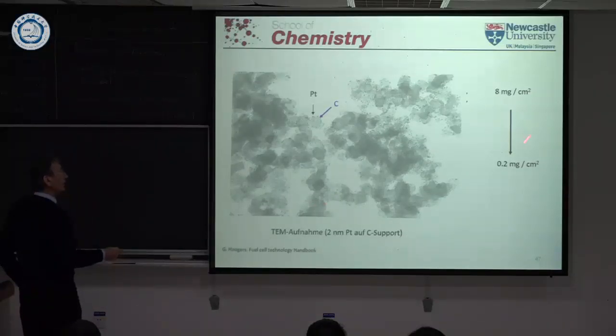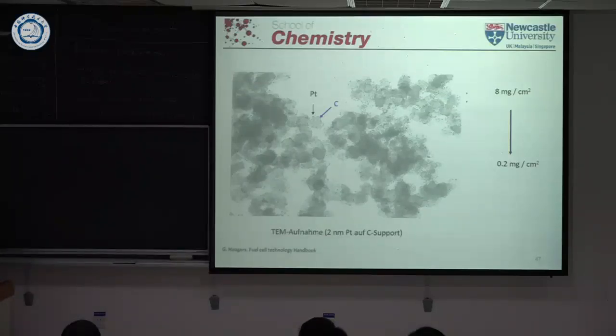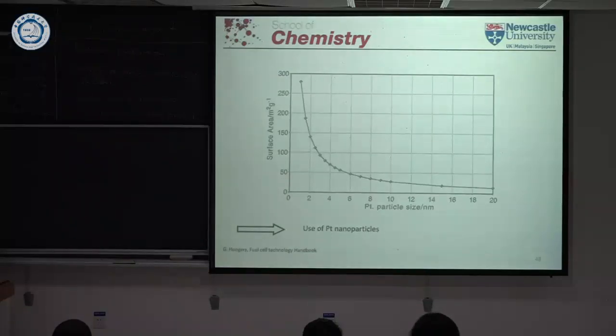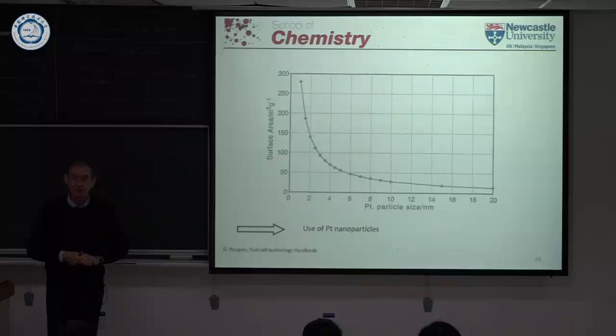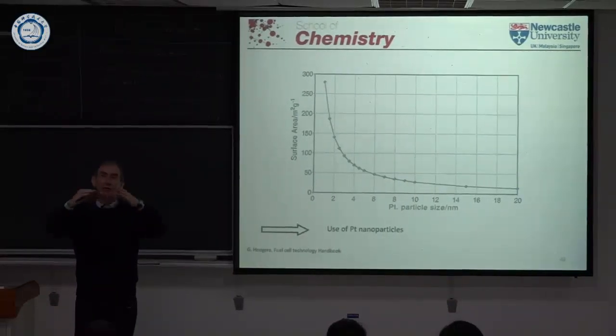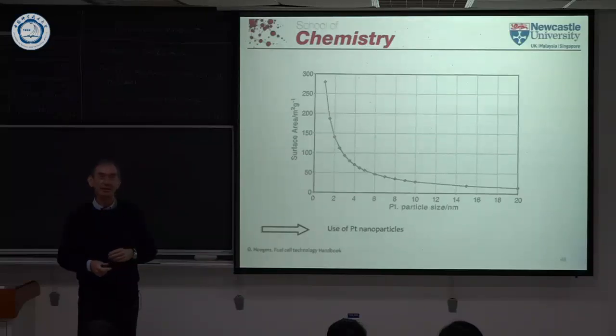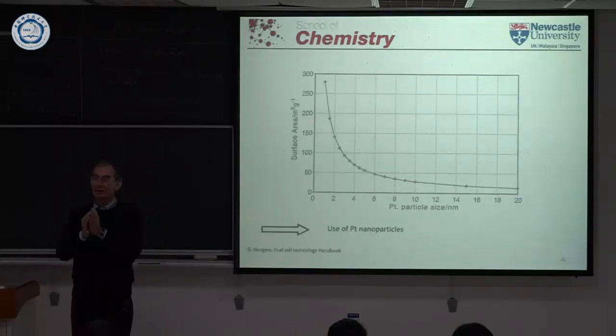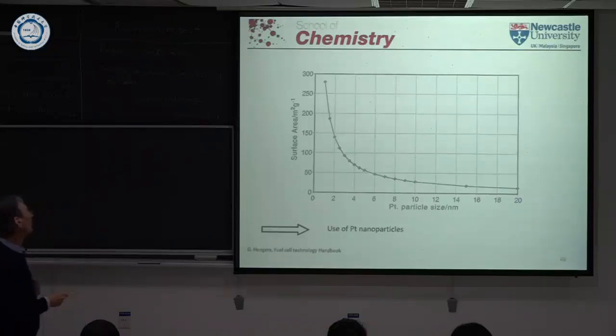And then you can vary actually the coverage, how much metal you put actually per square centimeter. That's shown here. That's sort of the variation, 8 milligram down to 0.2 milligram. Now I told you before, since platinum is such an expensive material, the ideal situation would be that you have only surface atoms, but of course that's not possible, right? So you have to consider how much of surface versus bulk I have, and I use actually in the catalyst particle only the surface atoms. And this shows you actually the relationship between the surface area and the particle size.